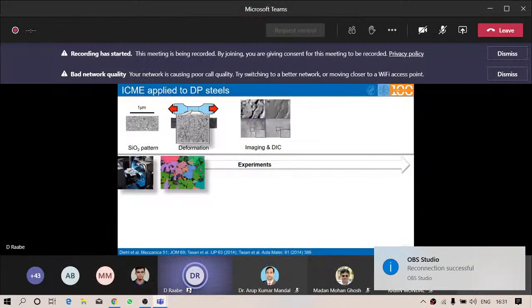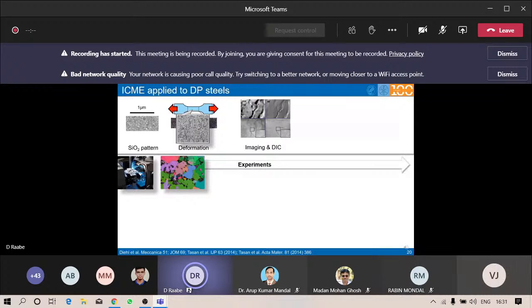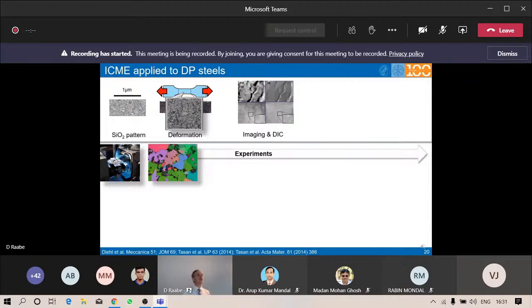Let me show you one workflow more starting at the microscopic level. So we have, for instance, like shown here, a scanning electron microscopy approach and microstructures. Again, we stay for a moment with dual phase steel. So you see again the fine ferrite grains and do this with an in-lens detector setup in the scanning electron microscope. Then you avoid this typical topography contrast that you otherwise get from such soft, hard contrast microstructures like DP steel. And then you get a much smoother surface appearance and your digital image correlation is not affected by surface topography.